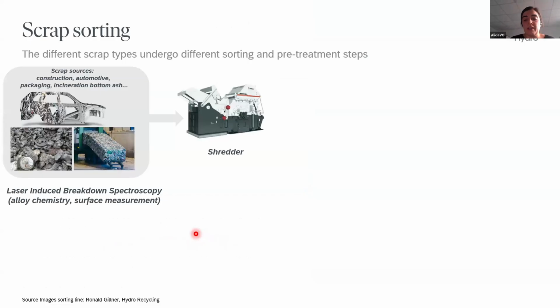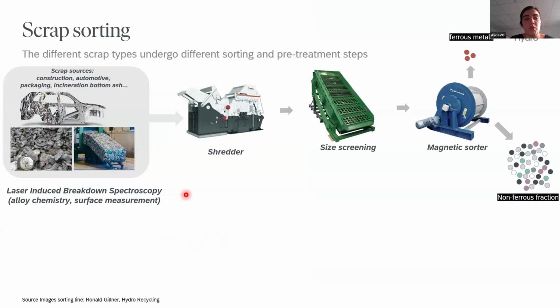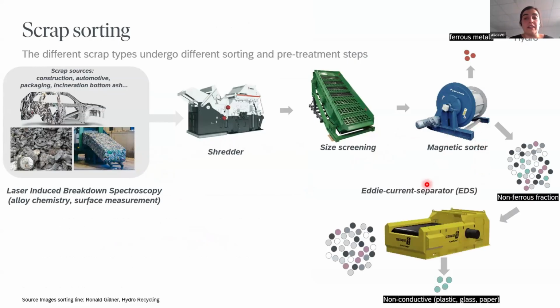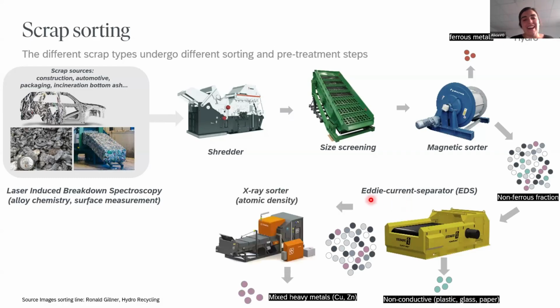This is a simplified sorting process where the scrap first of all is shredded and sifted into the right sizes for further sorting. Then ferrous metals are removed by a magnetic sorter. An eddy current separator separates the electrically conductive materials from non-conductive ones, like aluminium from glass and plastic. And then an X-ray sorter is able to separate heavy metals like copper and zinc based on the difference of X-ray absorption due to the different atomic density of these elements.